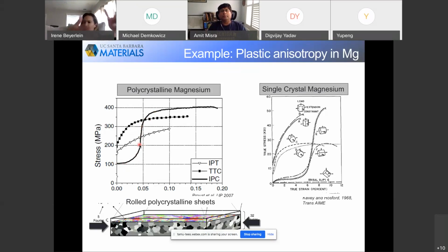You induce pyramidal slip within the twin domains. And at the same time, the easy slip systems that were activated in the matrix are starting to get constrained by the twin boundaries. So this rapid hardening happens. My point being that even if the twins were to saturate in volume fraction at this point, this hardening with continued strain could just be due to slip twin interactions.